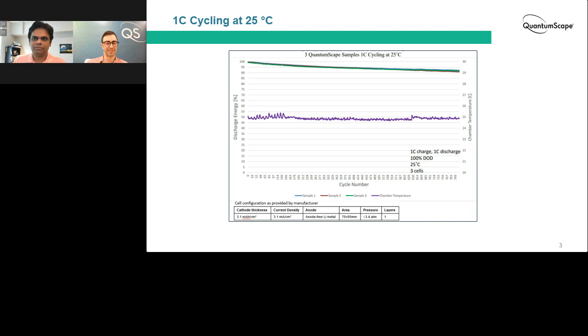The other details of the test condition are noted down here. The cathode capacity of 3.1 milliamp hours per square centimeter. What this means is the amount of charge that is accessed out of the cathode per area under these cycling conditions was characterized as 3.1 milliamp hours per square centimeter. At a 1C rate, that means the current density is 3 milliamps per square centimeter.